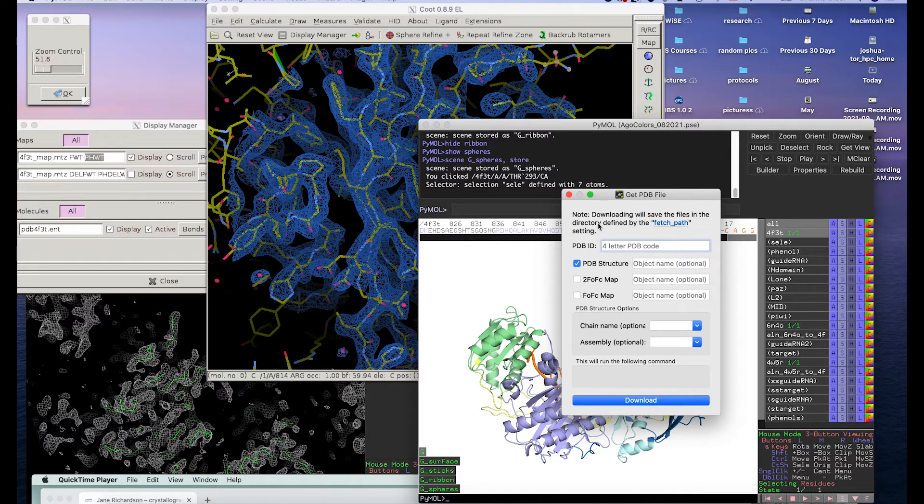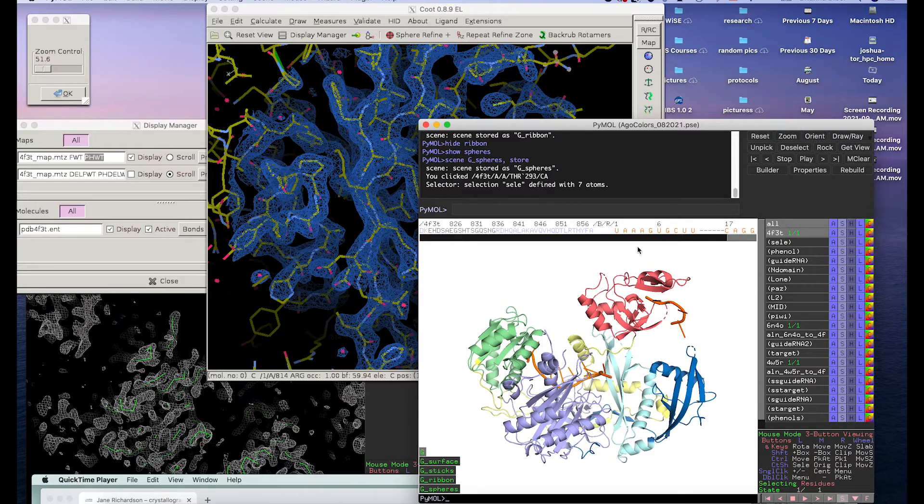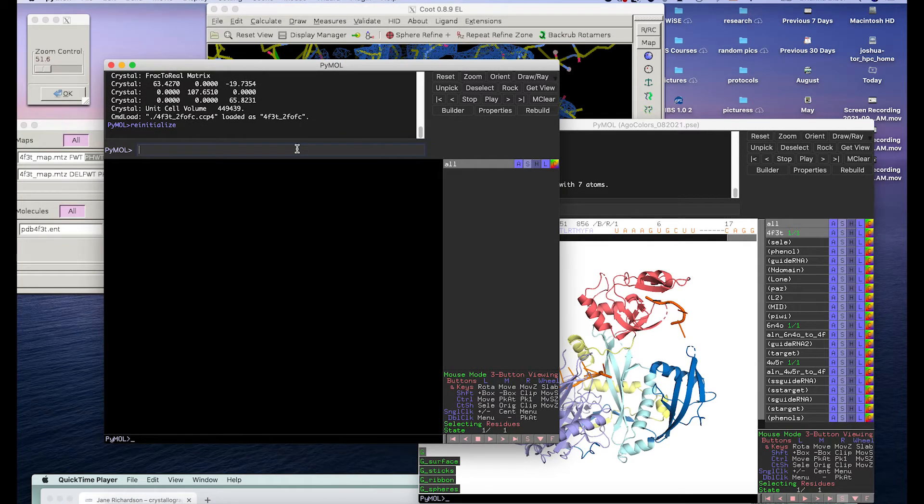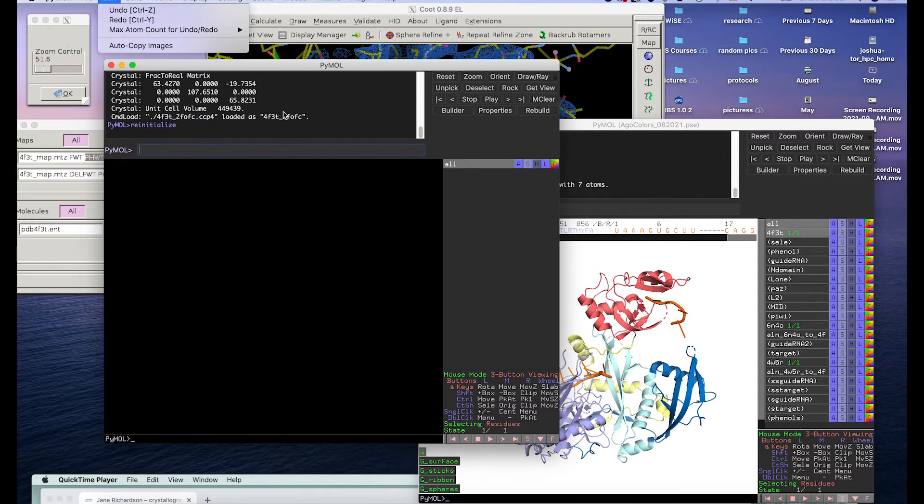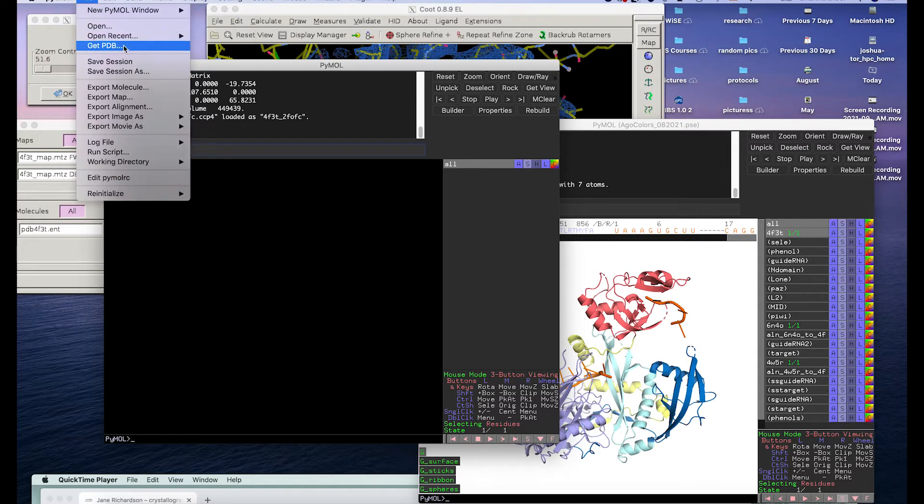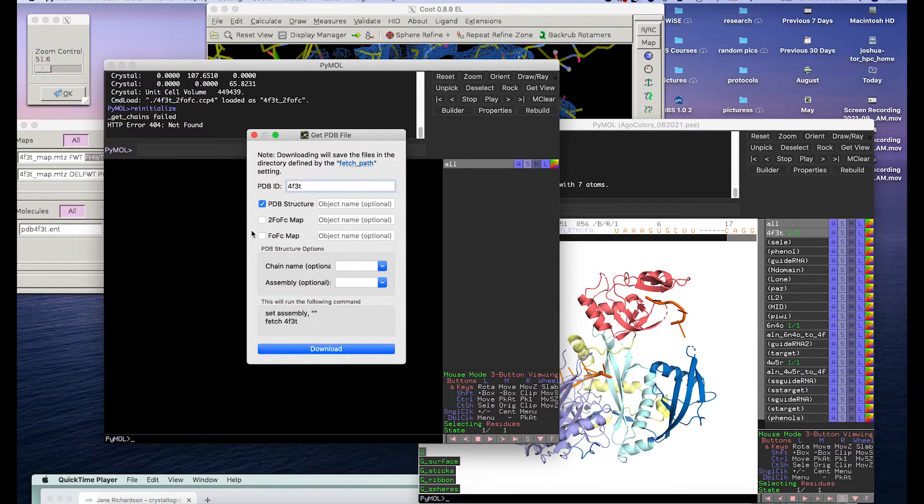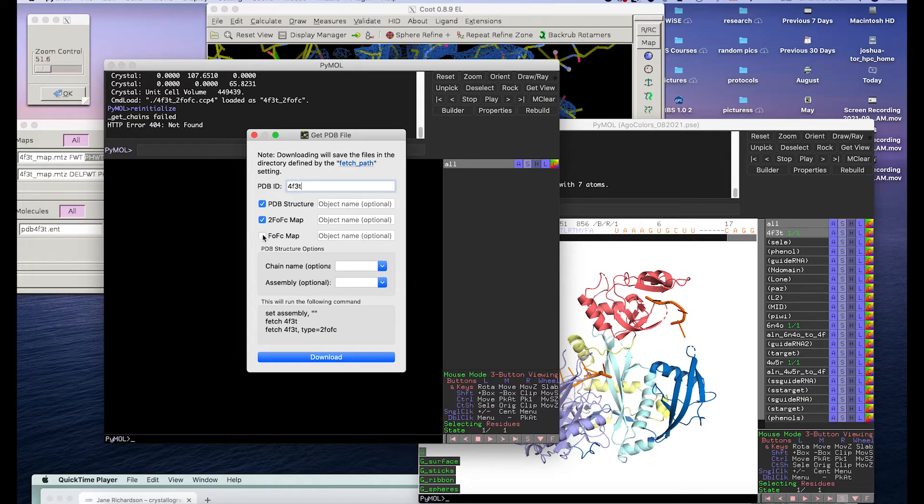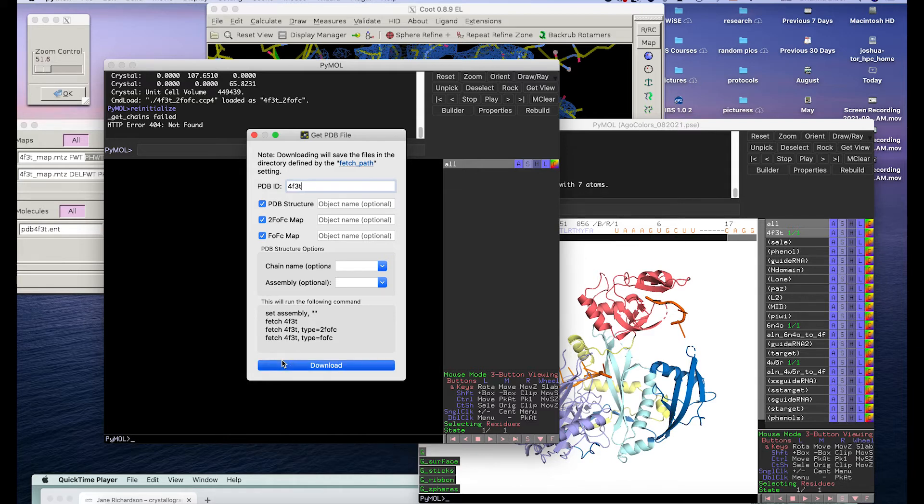And you can also do different commands, so you don't have to just do it from the GUI. But that's how you can then see this. So if I were to go and I were to get PDB, so if I do 4F3T, so this is the 2Fo-Fc map. So that's good for helping, this is the map that you normally see, and it helps minimize the bias from your model. So you're seeing it's two times the observed minus the calculated. When you do Fo-Fc, it's the observed minus the calculated, and so it's good for seeing regions that the map and the model disagree with, or so maybe there's additional things that could be changed.